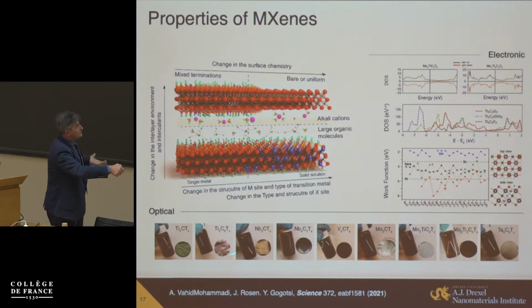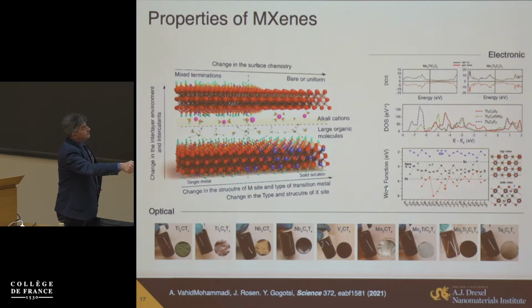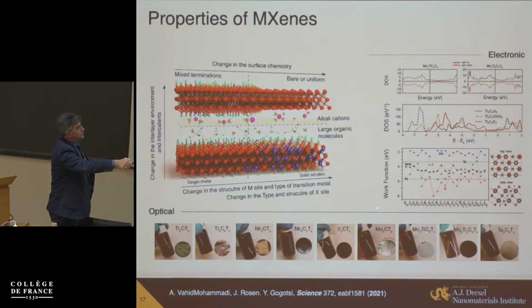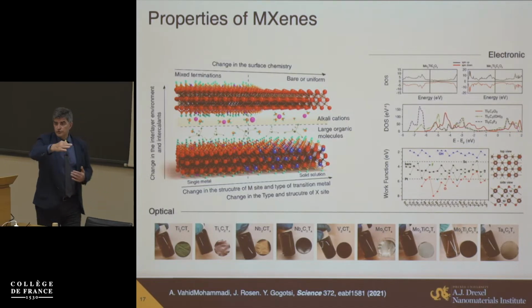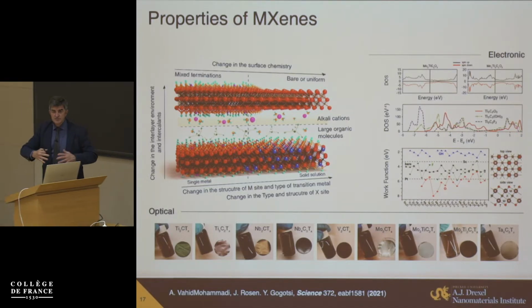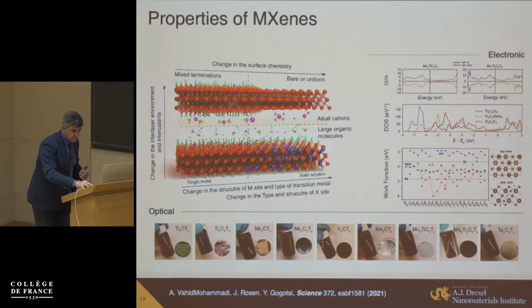But on other properties beyond plasmonic, for example, work function, which is very important for solar cells, other optoelectronic devices here. OH termination gives you 2 electron volt. Anneal your sample, remove hydrogen and get to oxygen, and you go to 6 electron volt. So again, you have a tunable work function just by changing surface termination in these materials here.